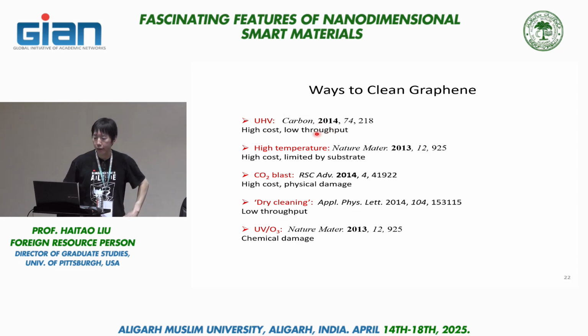And the example we did here, for example, is to put a dirty graphite sample in an XPS chamber overnight. We take it out the next day and find the carbon content actually reduced from 80 to 65-ish. So there is some kind of evidence of desorption of hydrocarbon. But this is meaningful if you work on a small piece of sample doing research, not meaningful if this is related to industrial fabrication. We also showed that if you apply high temperature, that helps to drive off the hydrocarbon.